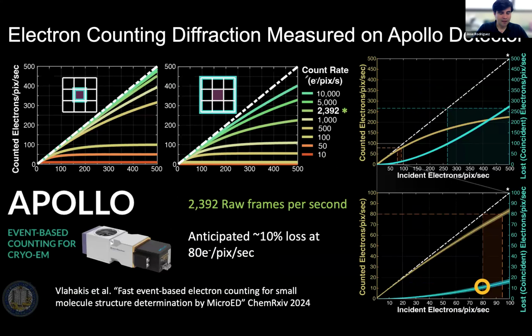We have been lucky to be able to test a lot of this on an Apollo direct electron detector manufactured by DE. It reads at a raw frame rate of about 2,400 frames per second. And we've been able to essentially simulate what the anticipated coincidence loss might be when you have an independent pixel or a correlated set of about 9 pixels. What you can appreciate from these graphs is that the number of counted electrons never matches the number of measured electrons, which are on the x-axis on the left-hand side of these graphs. Of course, the number of counted electrons plateaus, essentially dependent on the fundamental counting rate, or the number of frames per second that you're able to count.